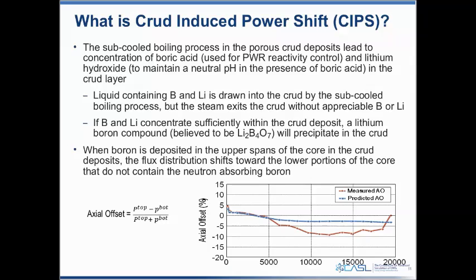With CIPS, you can see in the figure there, the blue curve would be our predicted axial offset, about -3% for the last 2/3 of the cycle. When we get crud deposition occurring, it takes some amount of time for the crud to get thick enough to actually result in precipitation of the lithium-boron compound. So in the first portion of the cycle, the measured and predicted axial offsets are in good agreement. Once we start to get thick crud deposits and boron deposition in the crud, the measured power distribution gets skewed toward the core inlet a bit.